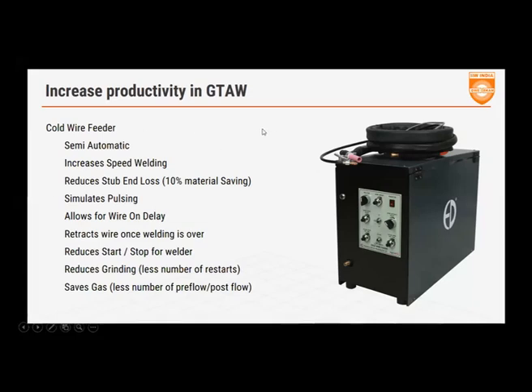The welders have a habit of feeding the wire in and out of the pool as they are used to. For the more skilled welders, the equipment can simulate pulsing for you. It can start the wire at a speed, pause for a time, again start, pause. The welder feeds in the wire only once the peak current is reached. So once you finish your upslope, you have had a smooth start and you reach the peak current, the pool is ready. At that time, you start feeding the wire into the pool. The same thing can happen here. You can synchronize your upslope time with the wire on delay, and the wire will start feeding only once the upslope is reached.